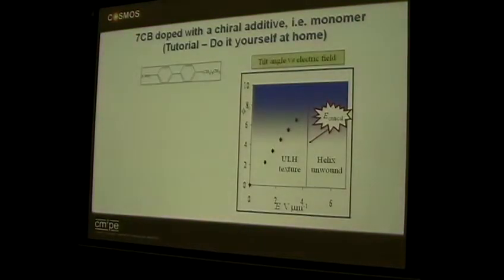Okay. So, I said any liquid crystal, take simplest, 7CB, it could be 5CB, pentyl cyanobiphenyl, discovered, done in '73, so nearly 40-something years ago, I can't count it. Any simple liquid crystal has a pear shape. Okay? You have a bigger volume there to the chain. And if you look at 7CB, you twist it up into a helix, you do see a flexo-electro-optic effect.